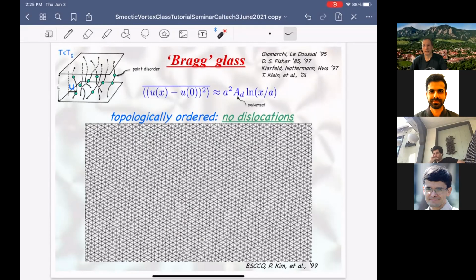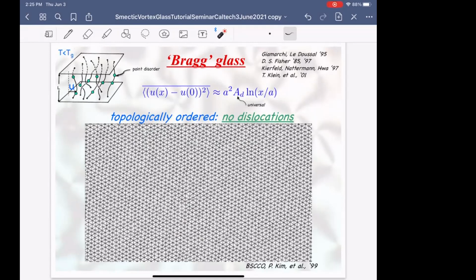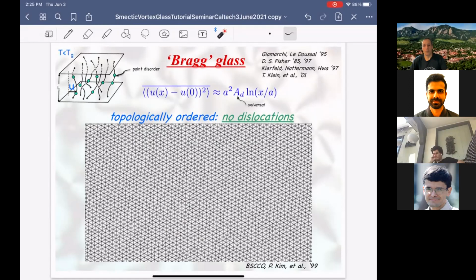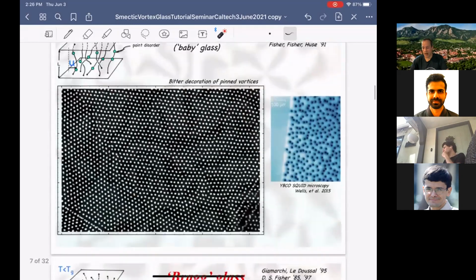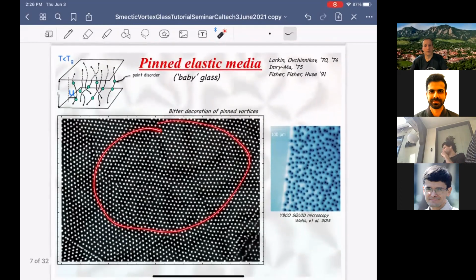In the same vein, one thinks about the Kosterlitz-Thouless phase as a phase that is disordered elastically, in the sense of Goldstone modes, has power law or logarithmic correlations in the phase field or displacements, but does not allow individual vortices. So this is sort of the disorder analog of that. One picture is that at low disorder you have an actual Bragg glass phase that's stable, which has no dislocations, and you can study its properties, as was done by Giamarchi, Le Doussal and many other people. But when you increase disorder beyond some threshold, this Bragg glass undergoes a phase transition, driven by disorder, to a vortex glass, which has a proliferation of dislocations.